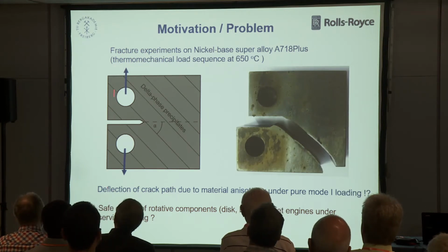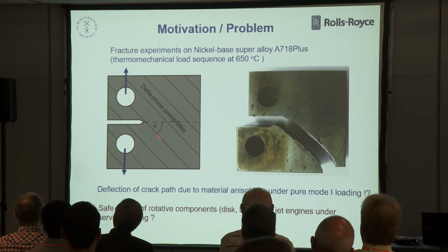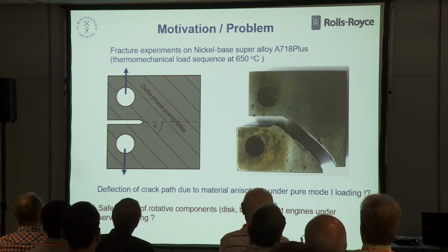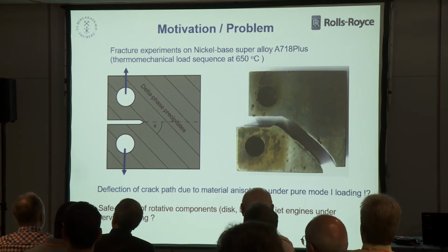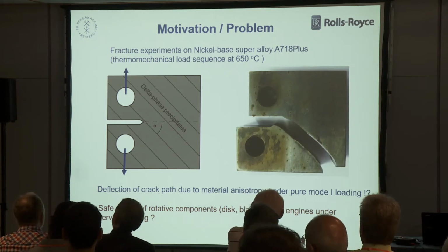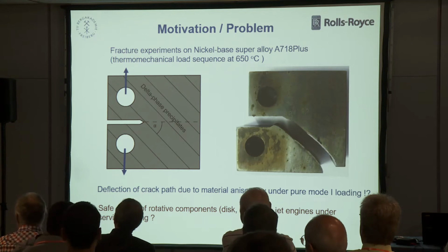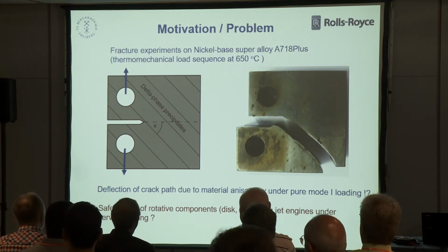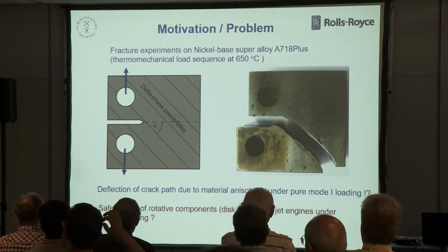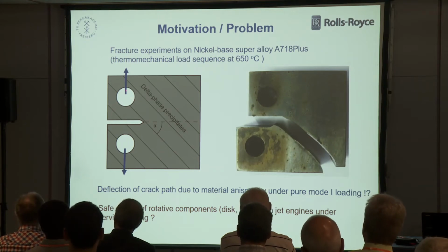So if you make a fracture test in mode 1 with a CT specimen in a cyclic experiment, a TMF experiment, then the crack deflects from the symmetry line. And this was a shock for the design engineers, because all their rules to predict or design these components are no longer valid. You didn't know where the crack will go and when it will start. So it needs research. The reason, I'll explain in a minute, is that we have some lines of delta